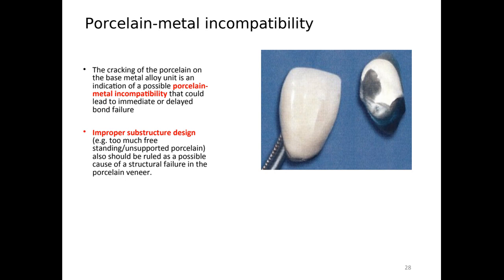Porcelain metal incompatibility is another issue that we have. The cracking of the porcelain on the base metal alloy unit is an indication of a possible porcelain metal incompatibility that could lead to immediate or delayed bond failure. So if the metal and porcelain are not compatible with each other, there might be a problem on bonding. Always check with the manufacturer of alloys what type of porcelain we can use for that alloy. Improper design of the coping: if we have a lot of porcelain that has no support from the coping, that also can damage the bonding of the porcelain to metal.